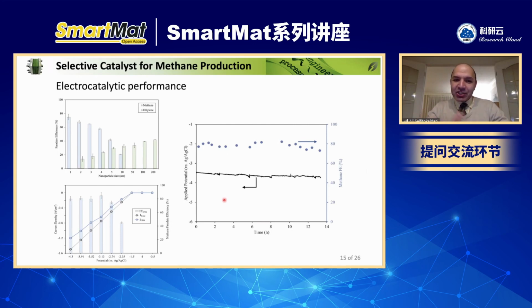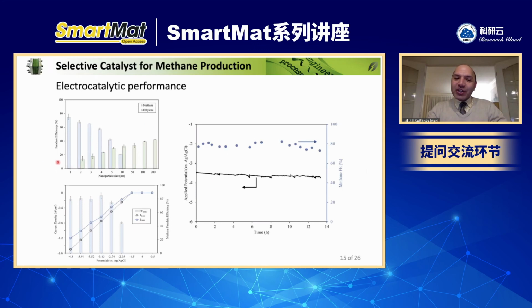But earlier I mentioned we were interested in methane for some reasons, green methane production in Canada, for example. But then we were also interested to investigate that small size that people haven't really explored that much, at least for the CO2 reduction reaction. I've been working on CO2 projects, but the smallest particle size that we were using was around 10, 15 nanometers. And even for those 20 nanometers, we were further doing electrodeposition to increase the thickness of the sample. So I was thinking, okay, nobody actually knows what we should get from copper at that small size, so let's just try it. And then we observed quite different products than what we were expecting at larger scale.